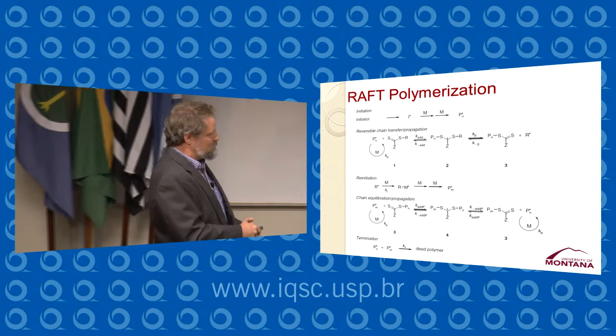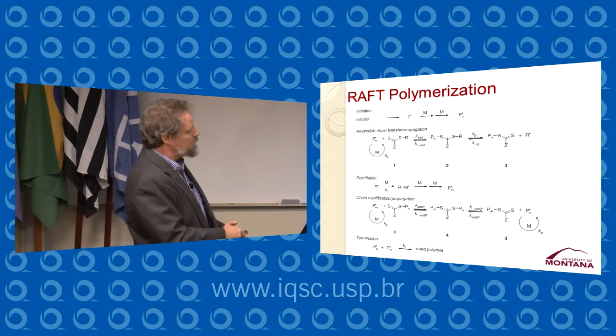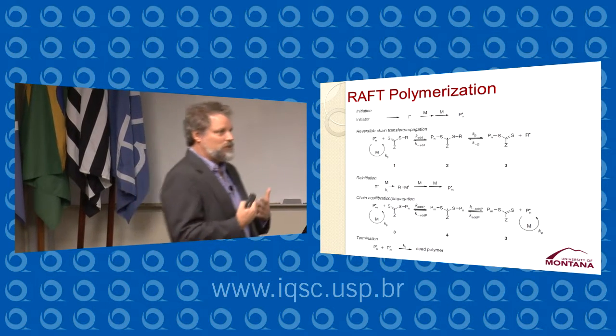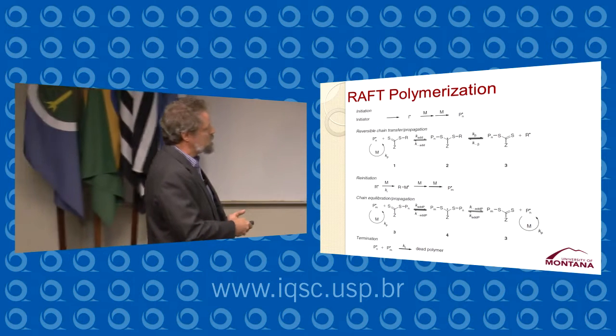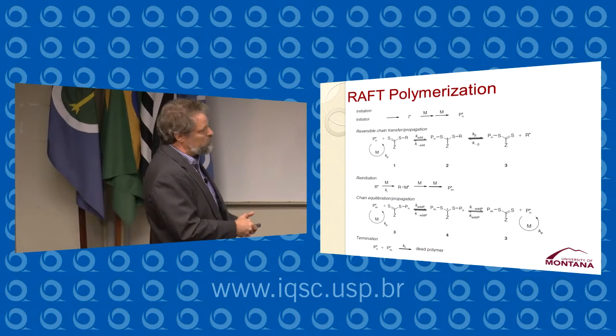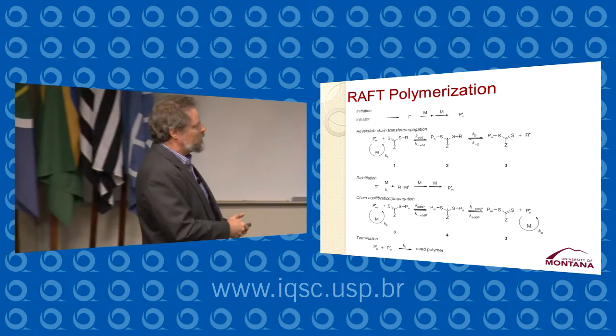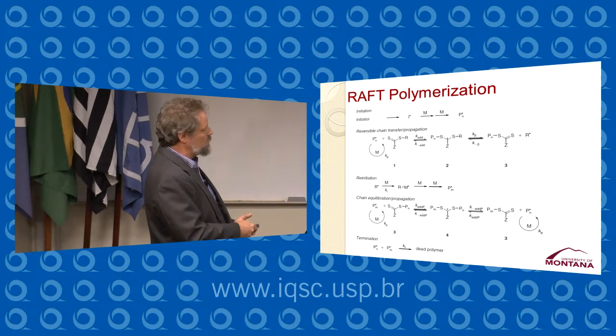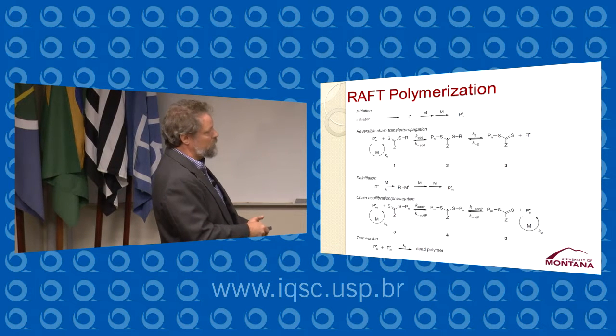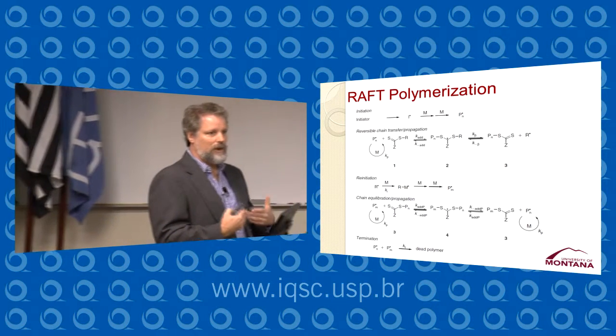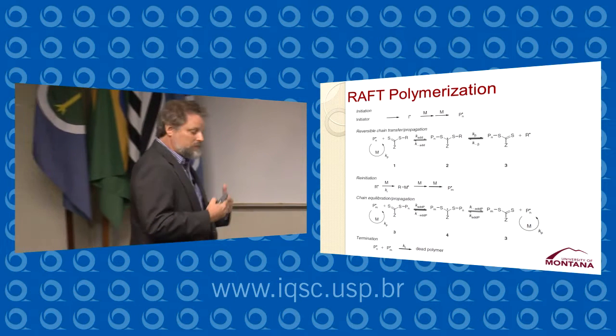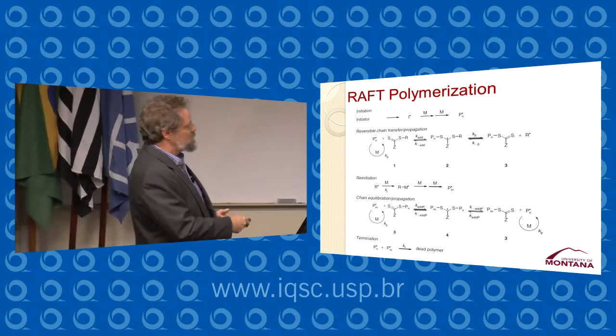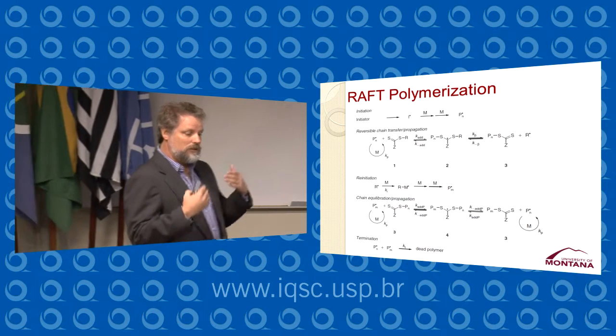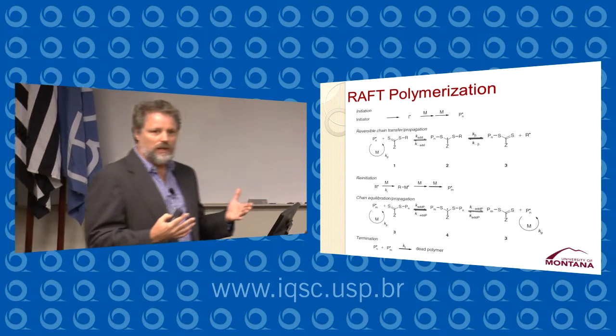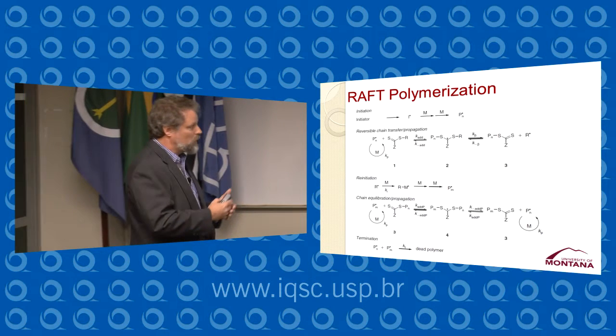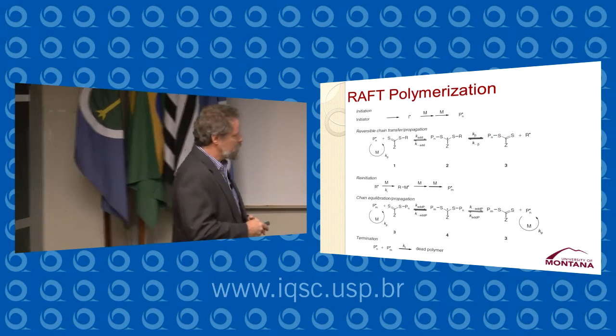Once this process occurs, then we allow this reaction to run. Polymerization occurs relatively slowly because the concentration of these growing polymer chains is quite low. We have most of our polymer in this form or this form, and very little in the form of active free radicals that are growing. So the polymerization occurs slowly. This is an equilibration process, which leads to all of the polymers having similar chain lengths, so we don't end up with a broad dispersity in our polymer chain lengths.